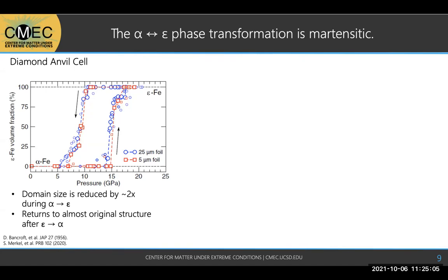This phase transformation was first found by Bancroft during explosive impact experiments, but since then, it's been studied many times, both with static DAC experiments and with laser shock and anything in between. So these on the left here are recent results from Merkel using diamond anvil cells.